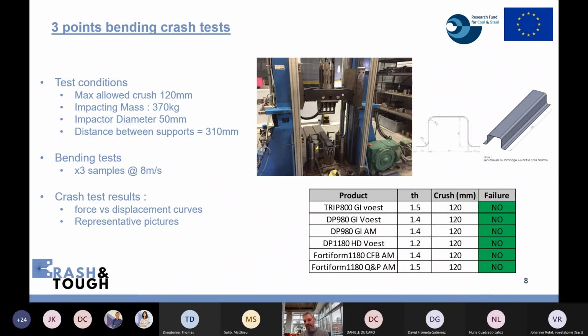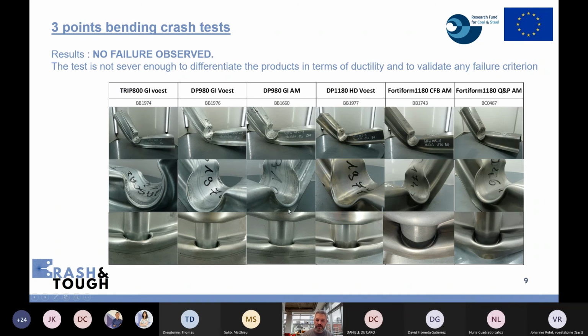And unfortunately, or by chance, or fortunately, it depends on the way you want to look at the result, no failure was observed on any materials. It means this test was not severe enough. Here we have the results. So we can have here the general view of the crushed sample, and here locally, when we look at the produced bent area, there is no failure. So unfortunately, this test is not able to differentiate the products in terms of ductility, and it is not a severe enough test to hope for a validation of the failure criteria that are developed by the partners of this project.